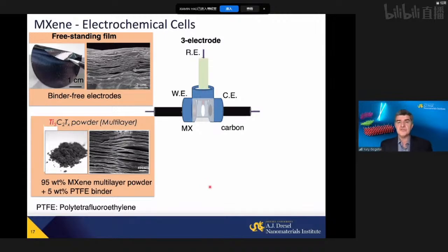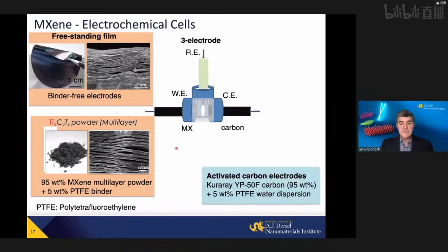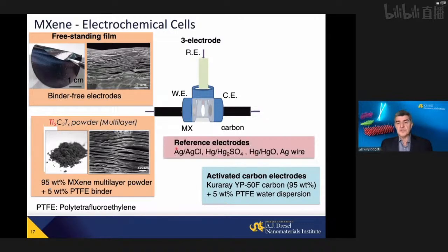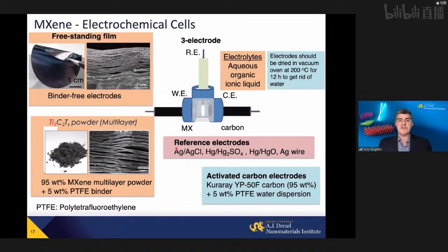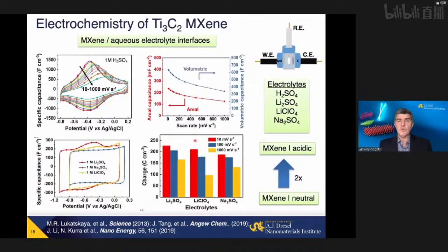With this, we can understand what is going on with the material and learn how to control it. Because keep in mind, we have dozens of simple compositions, a variety of surface terminations, and many more compositions that are possible, including solid solutions. So our challenge is to select which one is the best, how to control the surface termination, and how to design architecture. We can make freestanding films. Actually, MXene doesn't need current collectors for testing because of its conductivity. But we can also use multilayer powder and prepare electrodes in a conventional way, using, for example, polymer binders or just slurries on a current collector. Both are possible. In aqueous systems, we usually use activated carbon as the counter electrode, and a reference electrode in a 3-electrode cell, experiments from which I'm going to show you now.